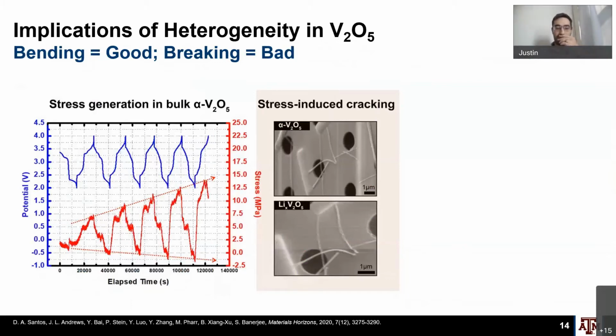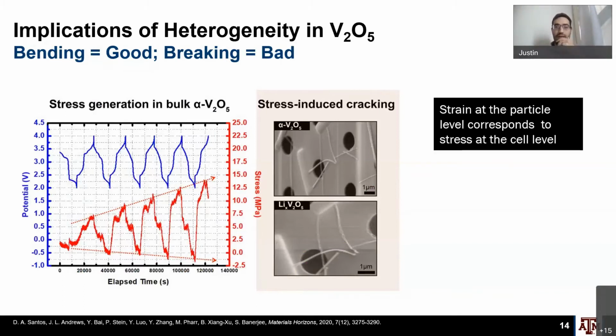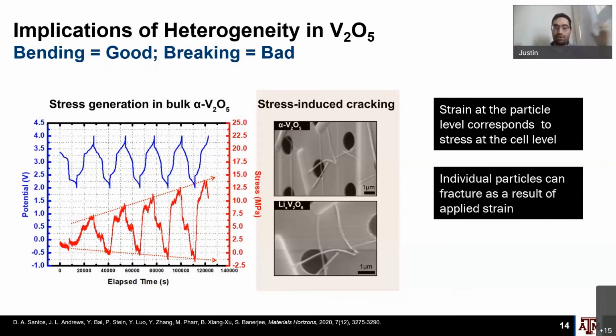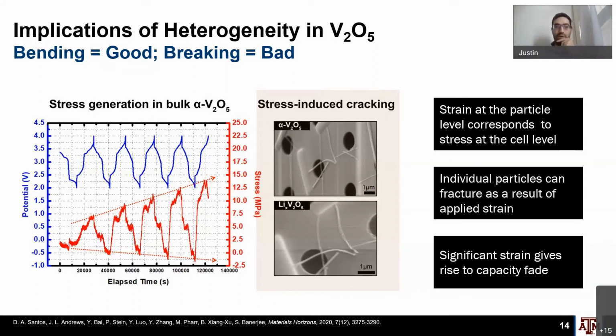This is work that was pioneered by David Santos, another member of the group. He was able to FIB down one of these V2O5 nanowires, and it has a bend in it. Then as a function of cycling, we were actually able to see these things fracture and break as a function of lithiation volume expansion and the strain that takes place. So in terms of thinking about the battery as a whole, this is really something that we want to mitigate.